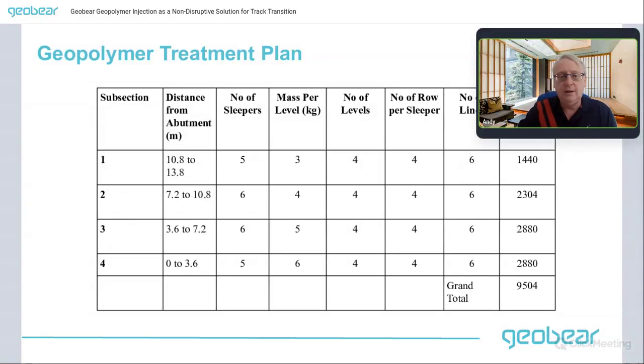And the injection quantities were varied. So I showed in the different subsections what the kilo amount would be. In subsection 1, we had 3 kilos per level. In subsection 2, we had 4 kilos. In subsection 3, 5 kilos. And then in subsection 4, 6 kilos. So we effectively doubled the amount of geopolymer from the first zone to the last zone. So we're increasing the mass, and by increasing the mass, you're increasing the stiffness. And these quantities and the model prediction outcome for strength were what were put into the Plaxis model to show the change in the strain.